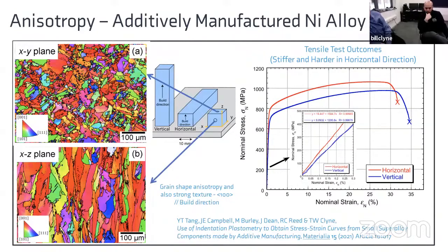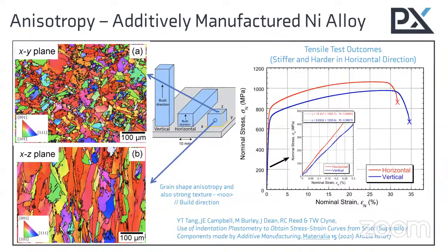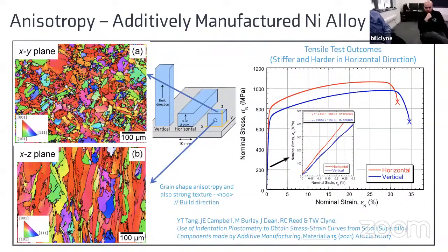Certainly, the texture is quite strong. You can see that here just from these EBSD. I think there's a factor of about 4 from randomness in terms of the bias of 100 directions being aligned along the growth direction. So it's quite a strong texture, quite a simple one actually, but it's not simple to predict how that will plastically deform. You would need to do some kind of crystal plasticity simulations, maybe. Yes, it can be done, I'm sure. But all we're seeing is the net outcome here. And you're quite right, it could be getting influenced by both shape anisotropy and texture.